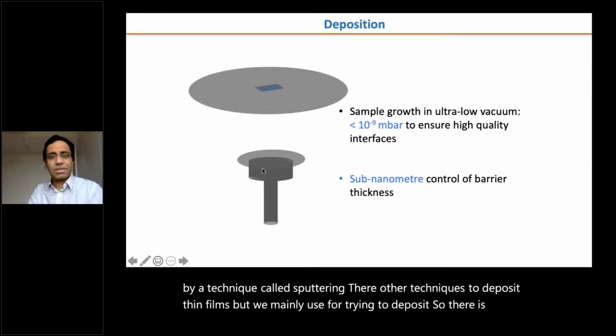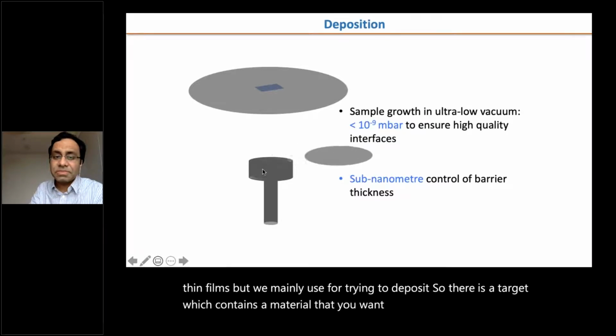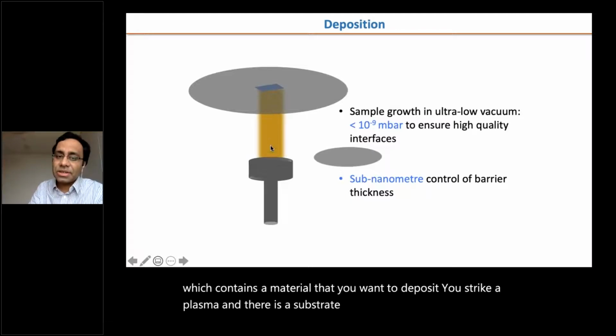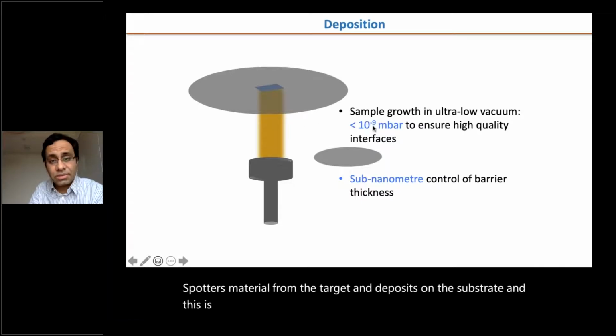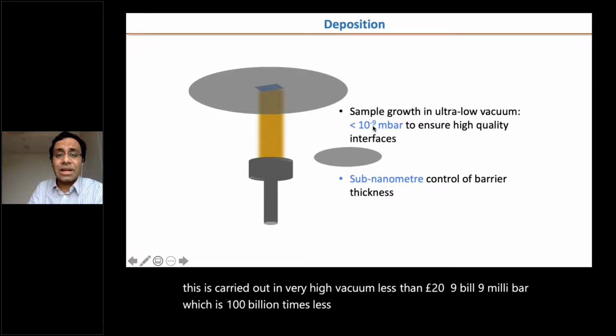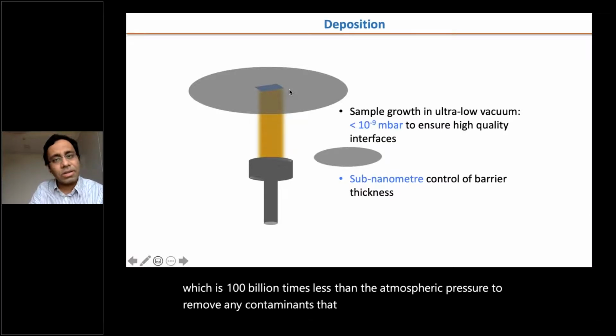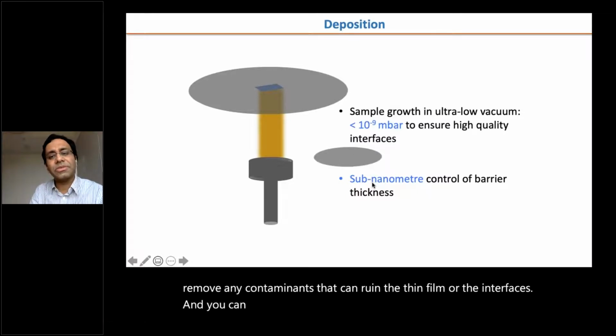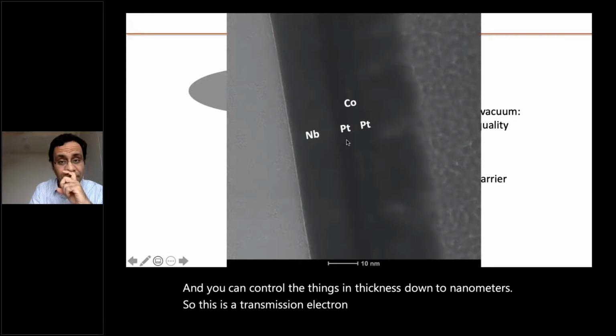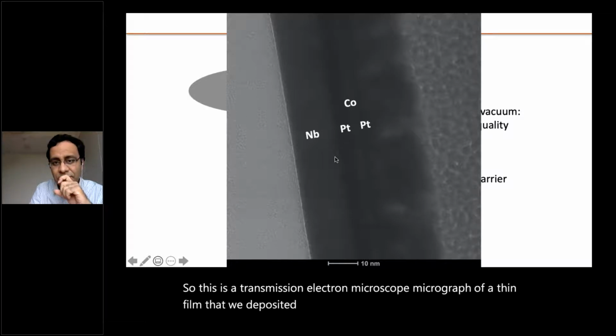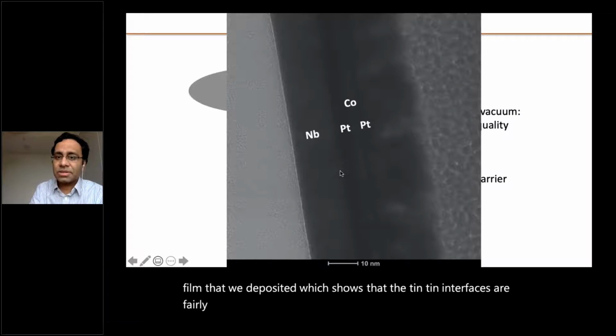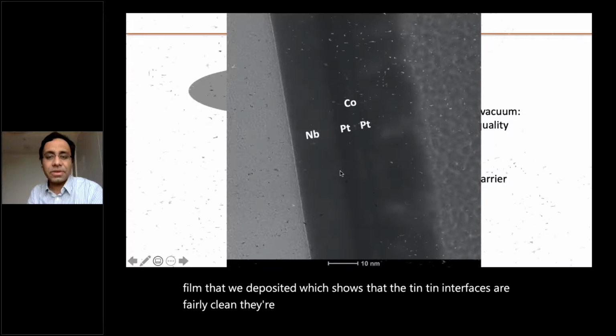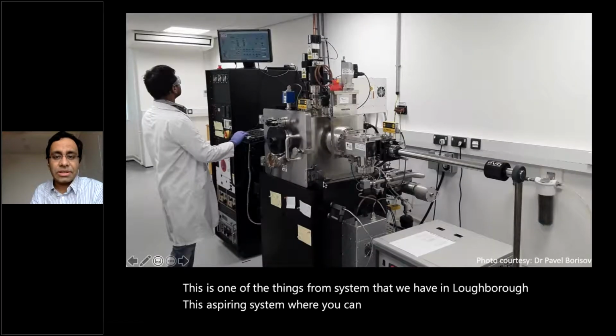There is a target which contains the material that you want to deposit. You strike a plasma, and there is a substrate, and this plasma sputters material from the target and deposits it on the substrate. This is carried out in very high vacuum, less than 10 to the power of minus 9 millibar, which is 100 billion times less than atmospheric pressure, to remove any contaminants that can ruin the thin film or the interfaces. And you can control the thin film thickness down to nanometers. This is a transmission electron microscope micrograph of a thin film that we deposited, which shows that the thin film interfaces are fairly clean. They're not disordered. This is one of the thin film systems that we have in Loughborough, a sputtering system where you can deposit 4 different materials.